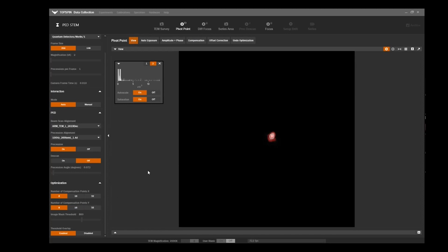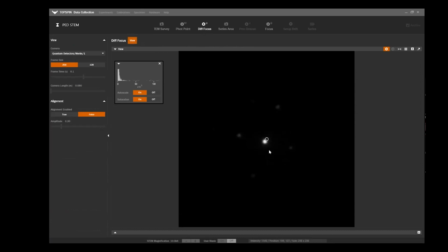But what I will show you now is basically just the automated alignment functionalities that are implemented within topspin. And this is actually one of the most amazing features I still find, because topspin right now is trying out different alignment parameters. And it's doing that much faster than a human can do. There's an algorithm that basically just checks at the same time if the alignment is nice and well. So we want to have a probe that's not moving on the sample, which is the case right now. So once I'm happy with it, or once topspin decides that it's fine, it will stop the alignment process. And we are good to go to the next step. I will switch the microscope to diffraction mode. So I hope you can see that on the projector upstairs, but we can already see a diffraction pattern. What I will turn on now is actually the rastering of the beam on the sample.